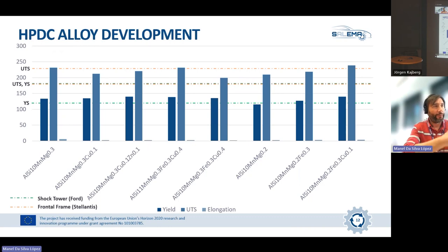Working on this alloy, in the previous stage we covered 15 different compositions, and then we selected the most promising ones. We went to our high pressure casting machine and cast testing samples, plates, that give us an idea of the properties we could reach on the final demonstrators. With those plates, we calculated the mechanical properties, and we observed that the values were pretty good.